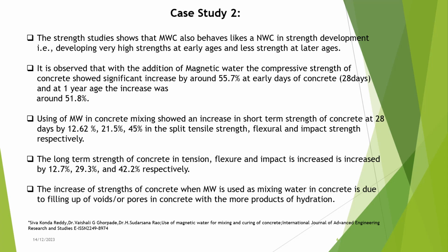With the addition of magnetized water, the compressive strength of concrete showed a significant increase, approximately 55.7% at 28 days and around 51.8% at 1 year. This suggests that the use of magnetized water positively influences the early and long-term strength characteristics of concrete.